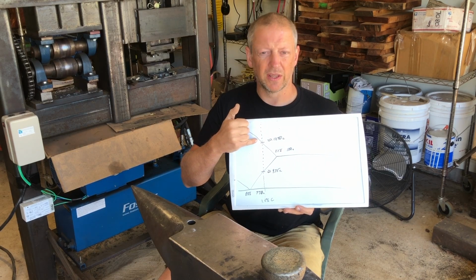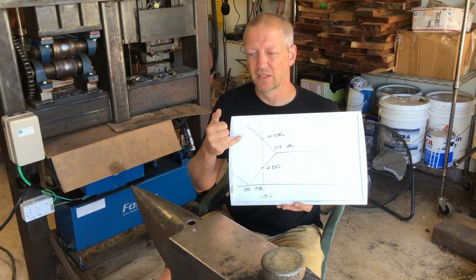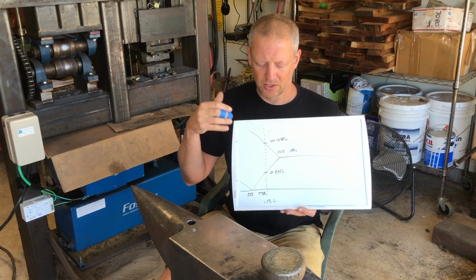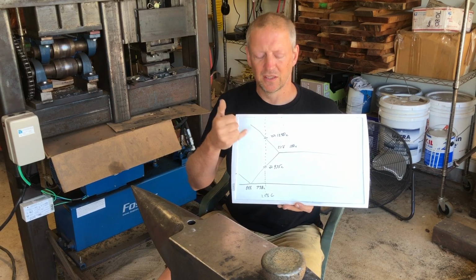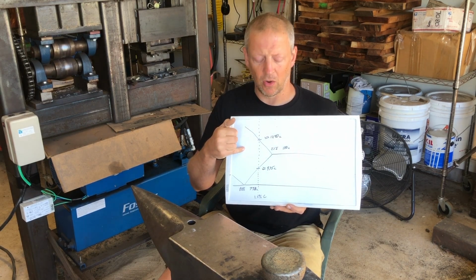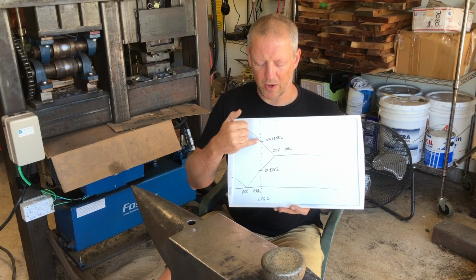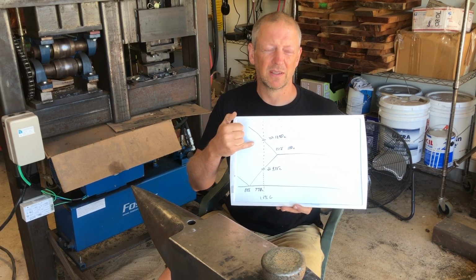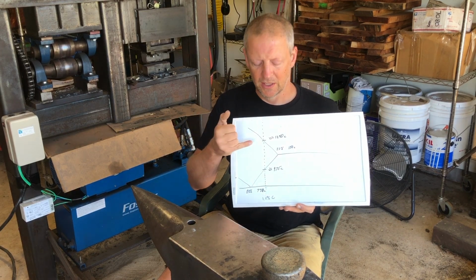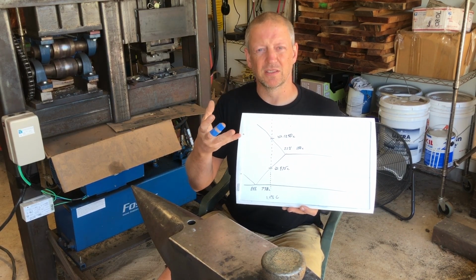Now, what keeps us from just instantly dissolving all that primary carbide? The answer to that is sort of twofold. One, we have a carbon concentration issue. During solidification, carbon segregated along with the other elements. The actual amount of carbon that austenite can hold is 2.2%. And what this means is that where we have higher concentrations of carbon, the carbides can't dissolve. There's no place for that carbon to go. So it's a slow process, because first carbides need to dissolve and carbon needs to diffuse away.